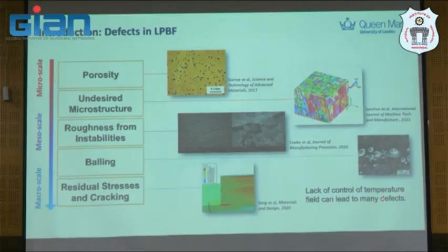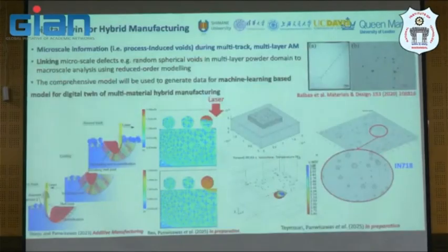But the lack of control of this, we hypothesize, depends on the control of temperature that you have to take care of. So the key is how can we predict the temperature accurately? What we do is try to propose a framework that integrates the information from the lower length scale, like the voids and the microstructure, to the larger length scale through something more like data-driven, or someone may call it a reduced order model. So reduce the complexity of the model to a certain level to make it a more rapid calculation, and then you can find a way to scale up your problem from millimeter probably to meter scale, something like that.